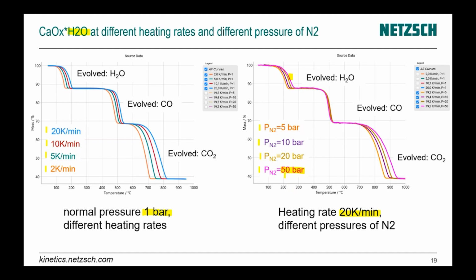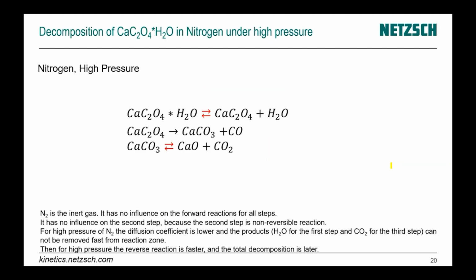And it means that high pressure of nitrogen will suppress the decomposition process for the first step, the release of the water. The second step, the release of carbon monoxide. Here we have no influence of pressure on the decomposition step, on the decomposition kinetics. And the last one is the release of carbon dioxide. Here again there is an influence of the pressure of nitrogen. Let's see what happens inside.